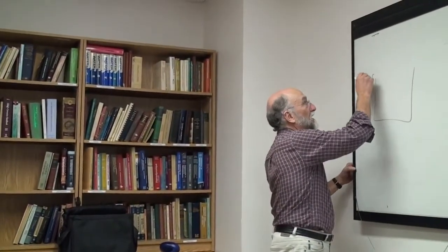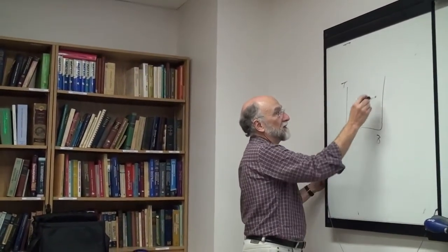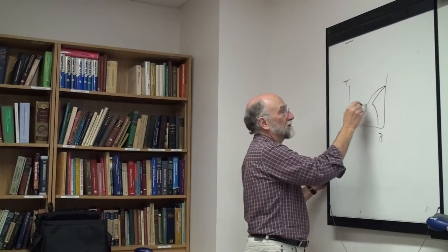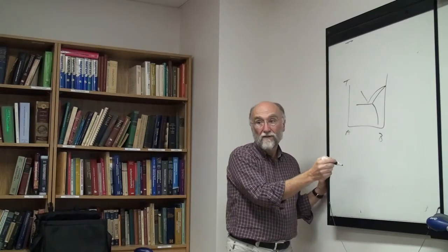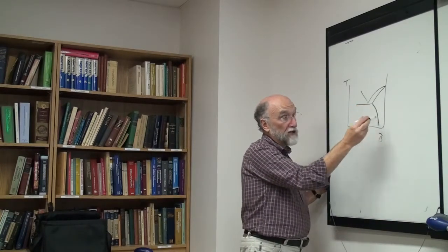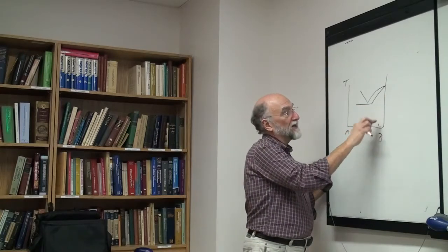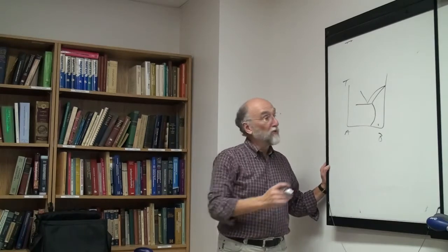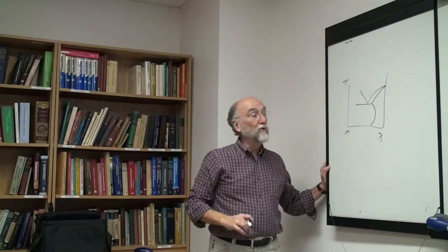It's possible, yeah. Solubility increases as temperature decreases? That was the example I showed called retrograde solubility. Normally you have a diagram that looks like this, so the solubility decreases as you go down, but it's not necessary. It is possible for that to go like that thermodynamically. You rarely see that, but there's no thermodynamic reason why that can't happen.